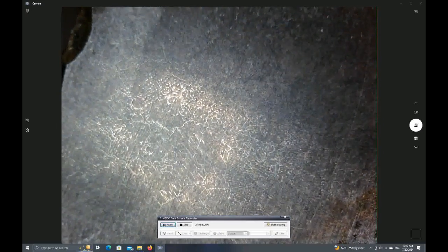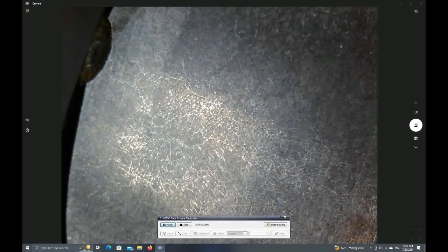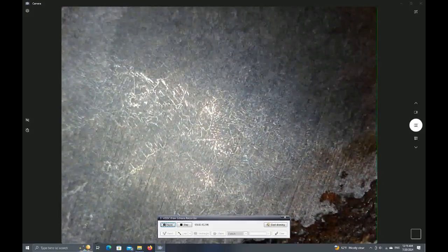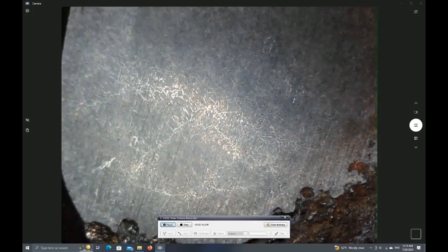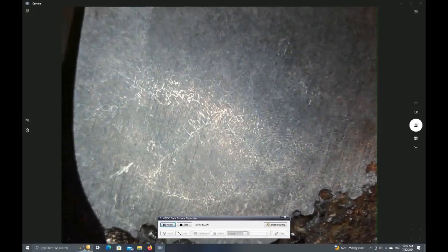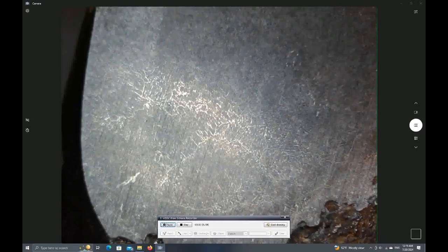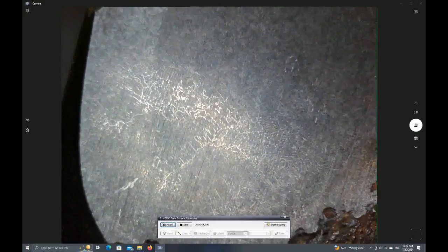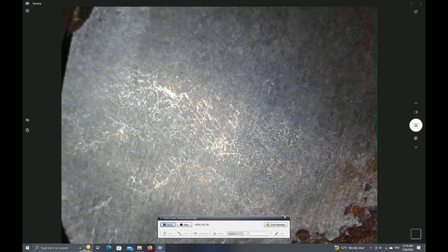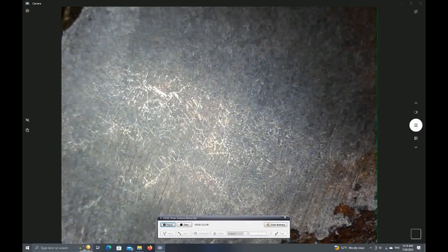So what we're looking at is, you can see a whole bunch of lines that almost look like country borders on a map. Those are humongous grain boundaries. Pretty cool features, which I've never seen before, but they do lend themselves to making a weaker forging because the light lines that you see that make those demarcations are basically carbide precipitation at the grain boundaries, and that becomes a local area where the melting point of the steel is lower.